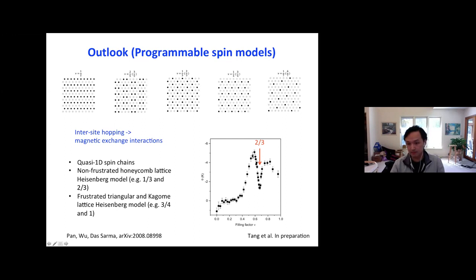And if you trust what I say here without showing the data, because I don't have that slide here, at the high temperature limit, even for filling factors away from one, the system is largely compressible in most of the region. It follows the Curie-Weiss law quite well in the high temperature limit. But it starts to deviate from the Curie-Weiss law in the low temperature limit. It actually deviates more compared to filling factor one. So is that some kind of signature that the system is developing some sort of metallic coherence to go into something like a Pauli susceptibility? I'm not so sure. Probably we just need to measure at lower temperature.